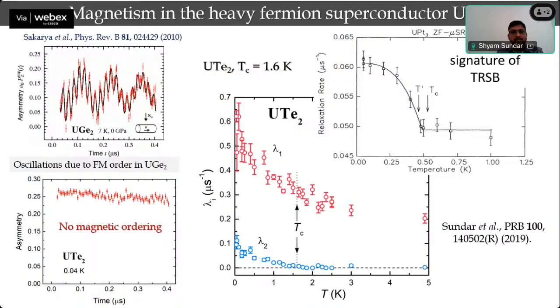So this basically tells that there are spin fluctuations in the system, but we cannot say for sure if it has time reversal symmetry breaking, because there are huge spin fluctuations in this system. So we further analyzed this temperature dependence of relaxation rate, and we basically found there are ferromagnetic fluctuations in this system, which are coexisting with the superconducting region in this sample.